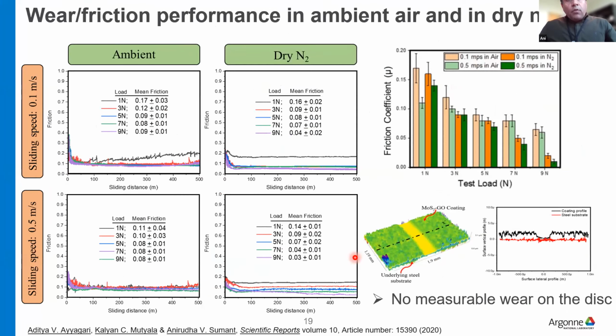So here are some examples of the tests that we have done. Steel against steel, rough surfaces of the steel, and silicon coupons, and we are doing this in different environmental conditions, ambient air and dry nitrogen. Here we are varying the load from 1 Newton to 9 Newton. And here we are varying the sliding speed up to 0.5 meter per second. And if you see here, as you increase the load and increase the sliding speed, the friction in both cases is dropping. On this graph, you can clearly see a nice reduction in the friction coefficient as you increase the sliding speed and also the contact pressure. That's counterintuitive, in the sense that if you increase the contact pressure or the sliding speed, the friction should increase, but the reverse is happening here.